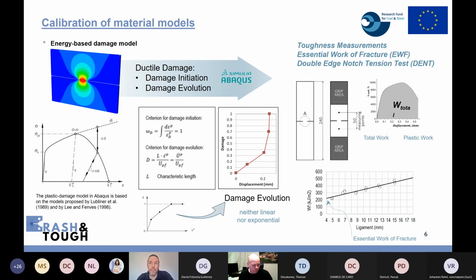The damage initiation is defined by an equivalent plastic strain, and when this value is reached, the element loses stiffness according to the damage evolution law. The damage is quantified by the damage parameter D that grows from 0 to 1, and when we reach this maximum value, the element is deleted from the mesh. The important thing here is that we calibrate the model using the DENT test, the double-edged notch tension test explained by David in the first session, and we are following the methodology for obtaining the toughness by the essential work of fracture. Next one, please, Jorgen.